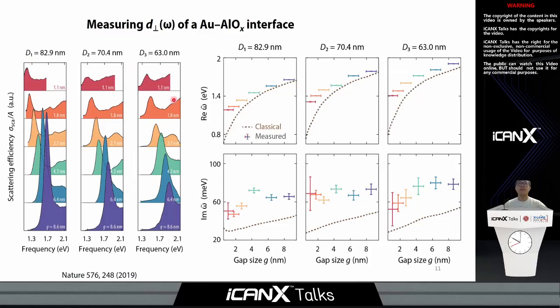For the real part of the complex resonant frequency, we find that there's a consistent blue shift of the resonance, consistent with previous measurements on gold. For the imaginary part, we find that there's a general broadening. But a key feature here is that the smallest gap size does not give us the largest broadening. This indicates that the surface response of this interface could be strongly dispersive.